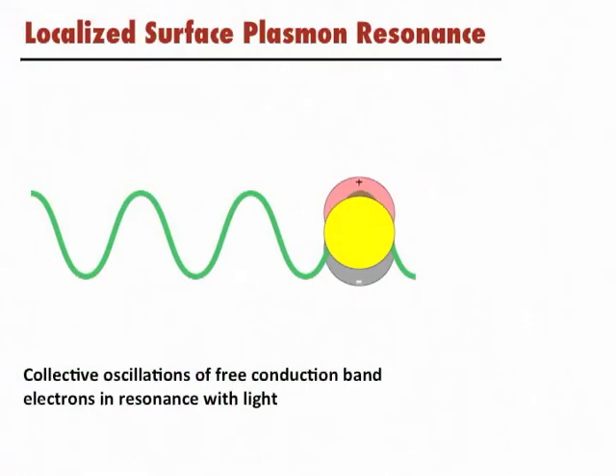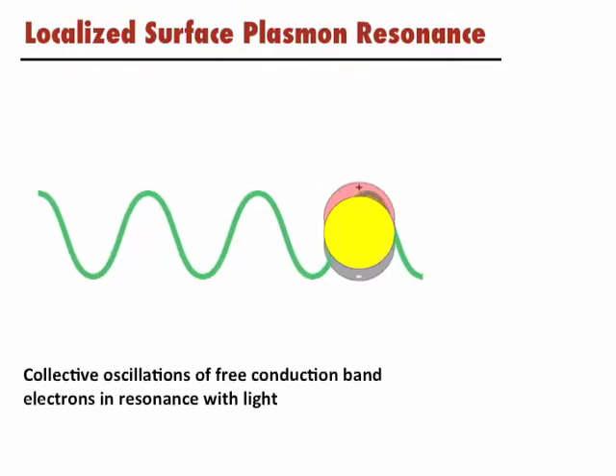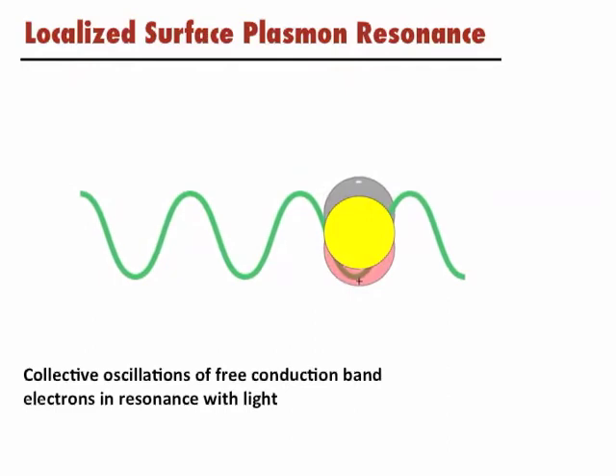The characteristic feature of colloidal metal nanoparticles is a localized surface plasmon resonance. The LSPR can be understood by considering a propagating electromagnetic wave incident upon the nanoparticle, whose frequency matches the plasma frequency of the particle. Excitation of plasmon-supporting nanoparticles using such a wave results in the coherent polarization of conduction band electrons, leaving lattice ions in their absence, and yielding large surface fields.